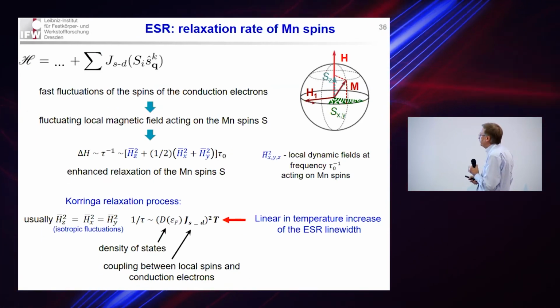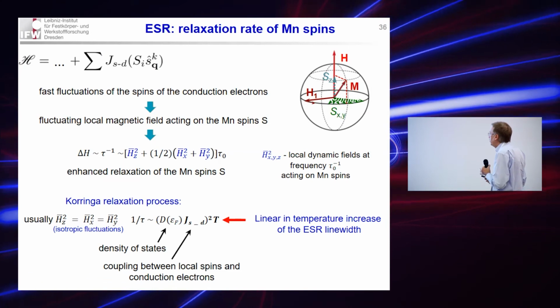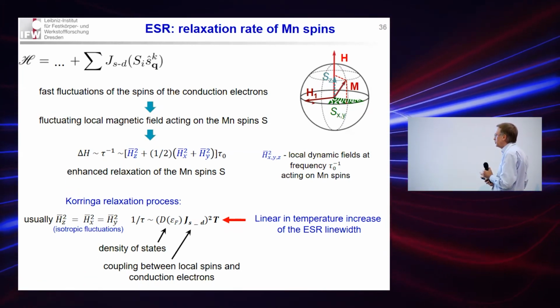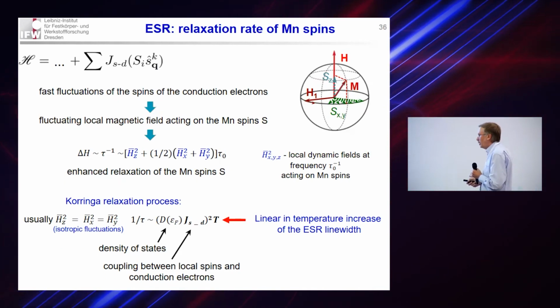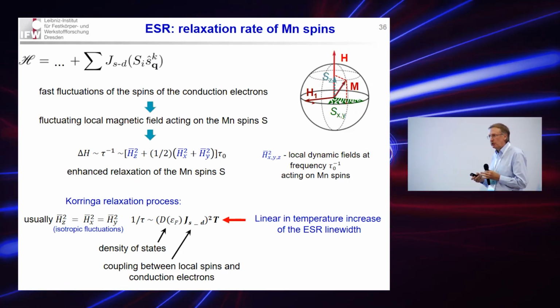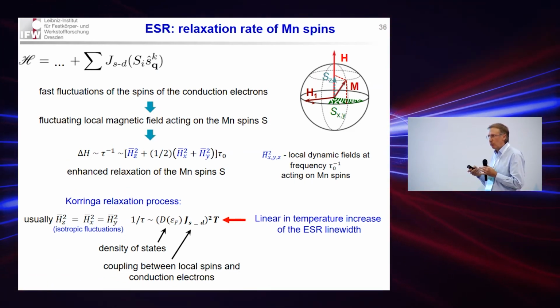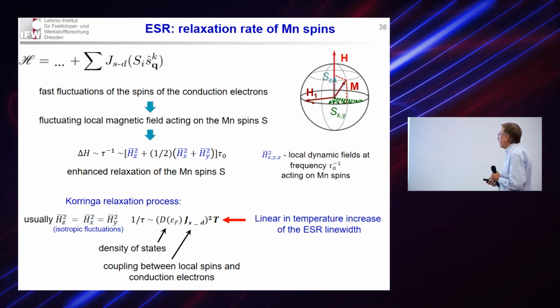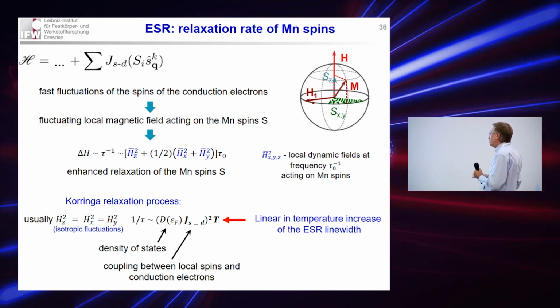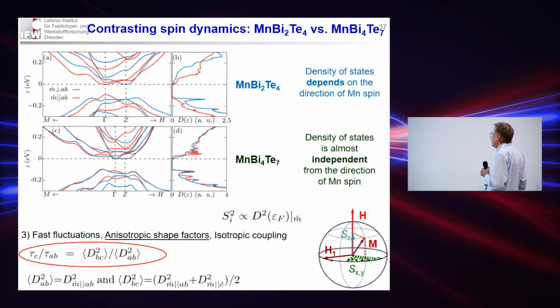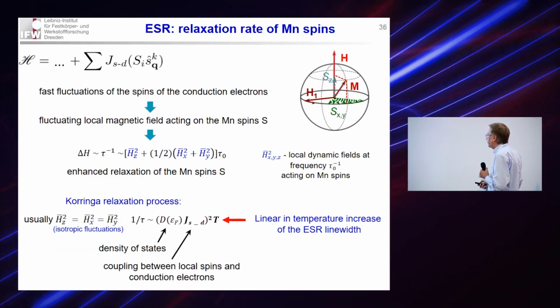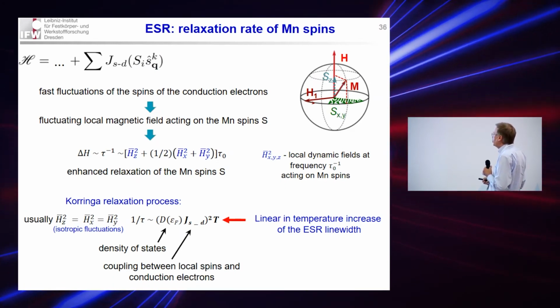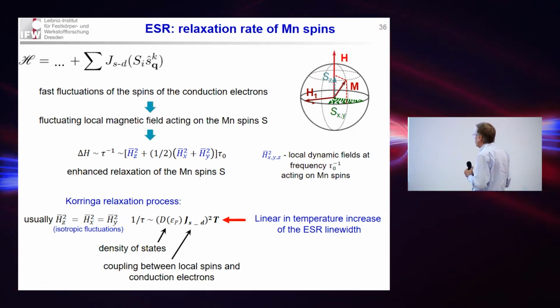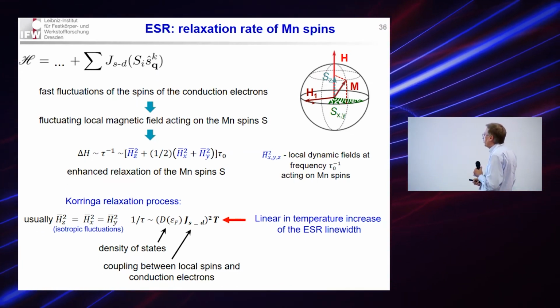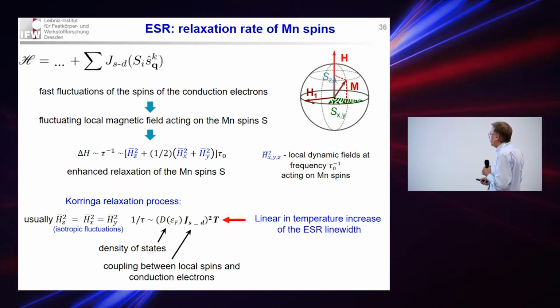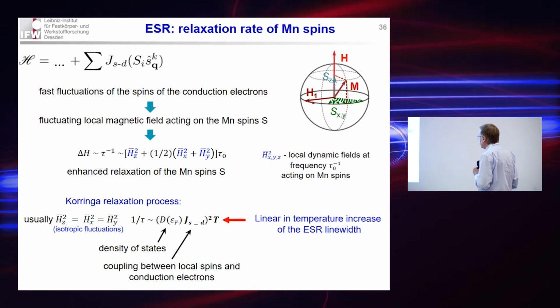Just to recall, the line width is given by the fluctuating field acting on the electronic spins. They could be generated by other degrees of freedom. And we also should recall that the materials which we study are not entirely bulk insulators. They were n-doped, so that they have some bulk electrons. And the manganese spins relax on these bulk conduction electrons. This is a very specific kind of spin relaxation, called the Korringa relaxation process: the spin flip on the conduction electron, which is linear in temperature, and its strength is determined by the density of electronic states and the coupling between the localized and itinerant states in the bulk.